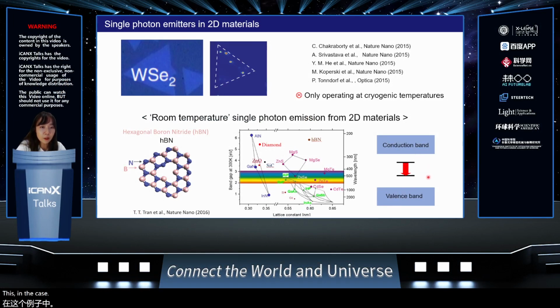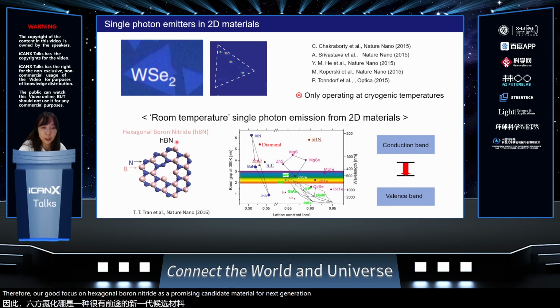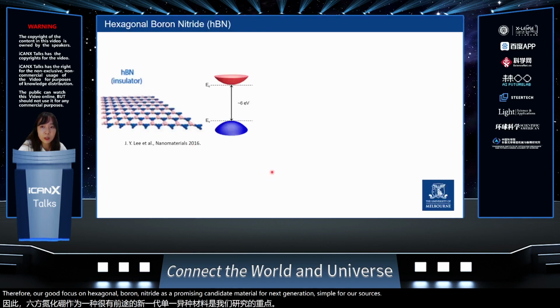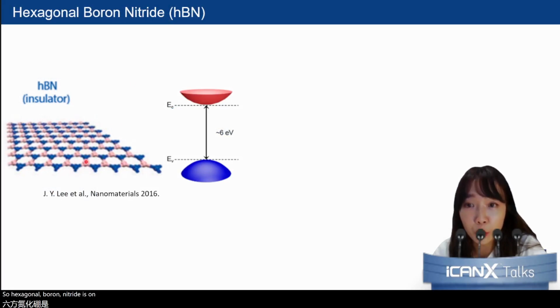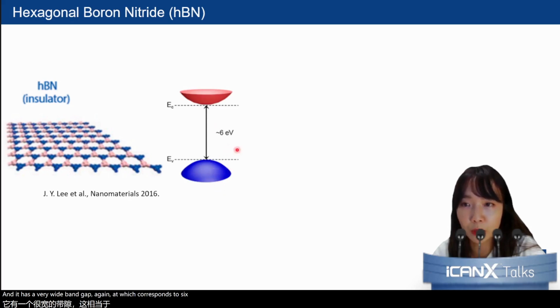This indicates that if you consider the thermal energy at room temperature, which is around 25 millielectron volts, that energy is insufficient to move the electron in the excited state to a higher state. Therefore, our group focused on hexagonal boron nitride as a promising candidate material for next generation single photon sources. Here's a brief introduction of HBN. Hexagonal boron nitride is a 2D material that contains boron and nitrogen atoms arranged in a hexagonal pattern, and it has a very wide band gap, again, which corresponds to 6 electron volts.